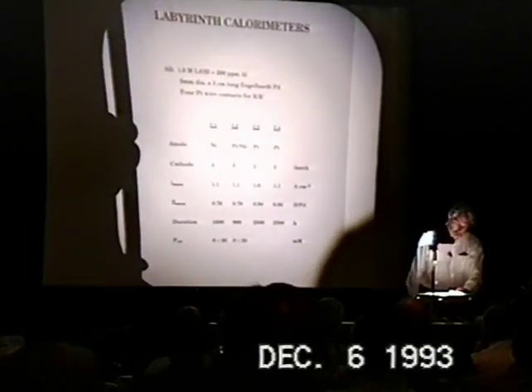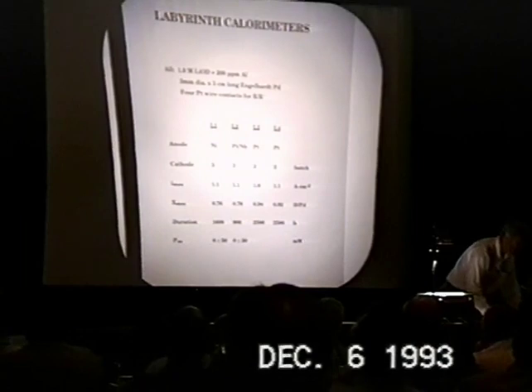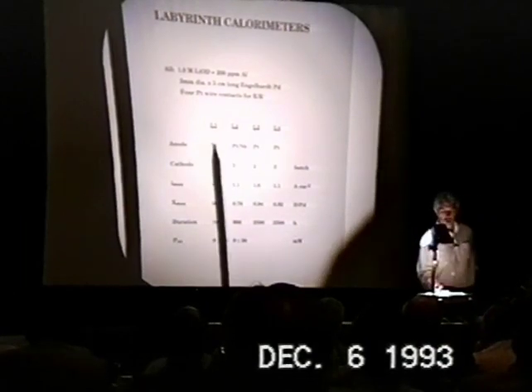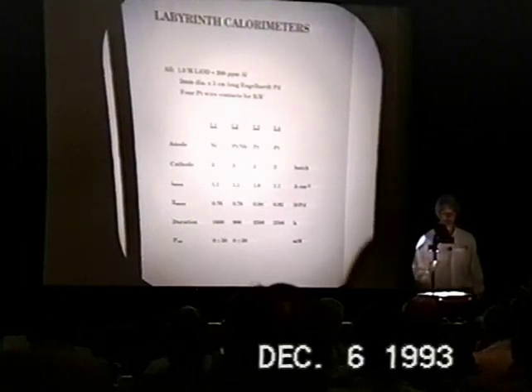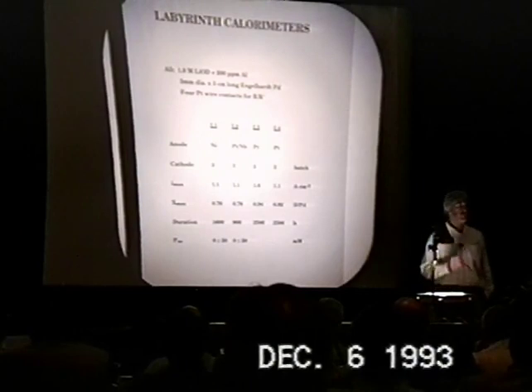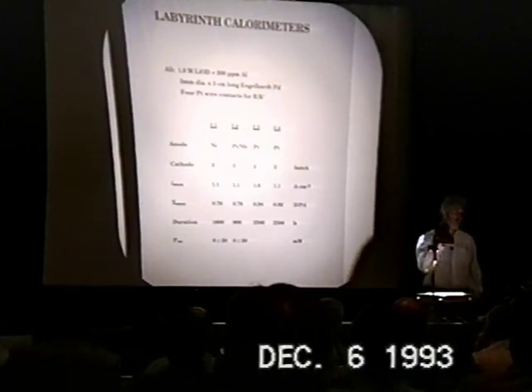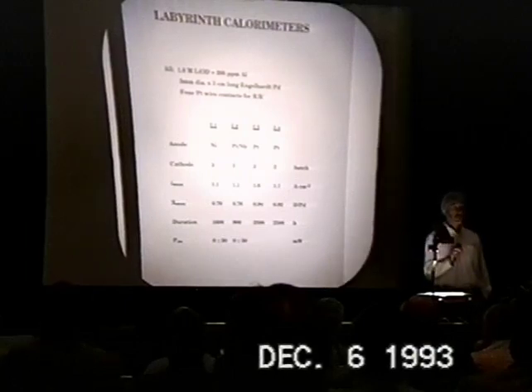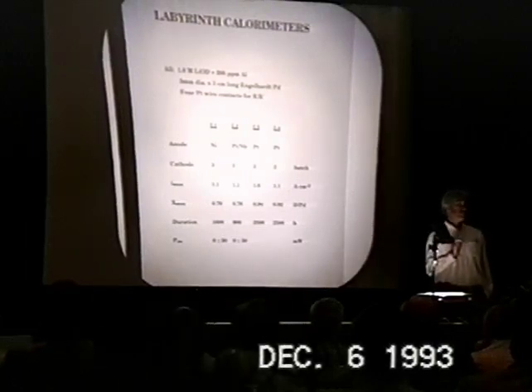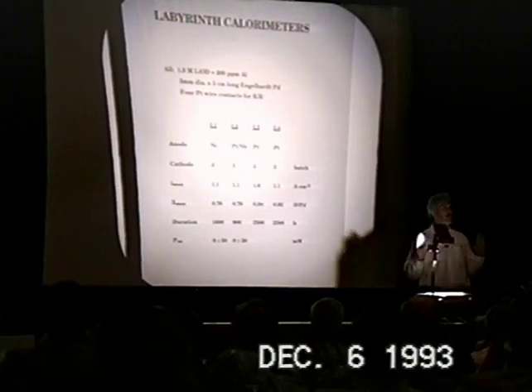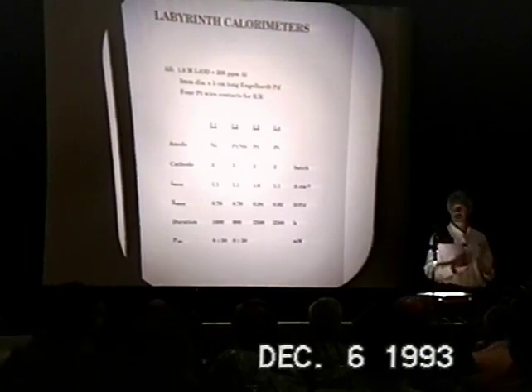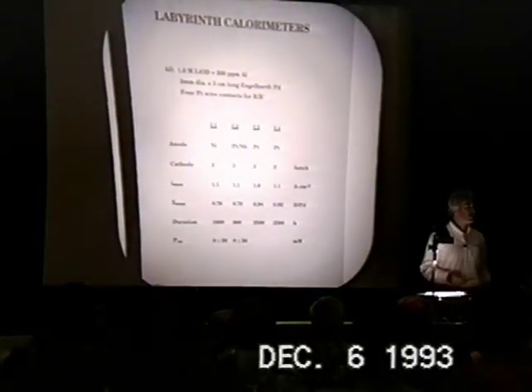Describe some of the results in our labyrinth calorimeters. Basically we ran 4 this year, which we call L1 through L4. We used a nickel anode for L1. In our experience, we have never been able to satisfactorily load a cathode that had a nickel anode. Other people may have other results, but we simply cannot get good loading if we use nickel anodes.